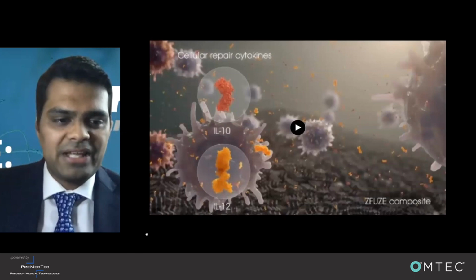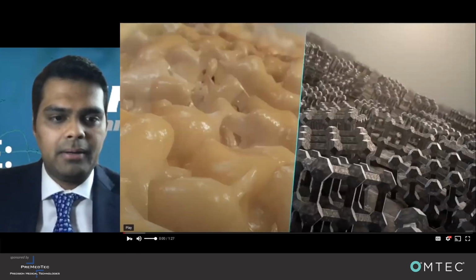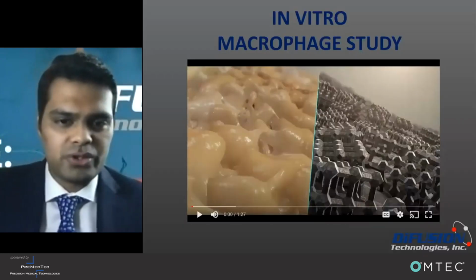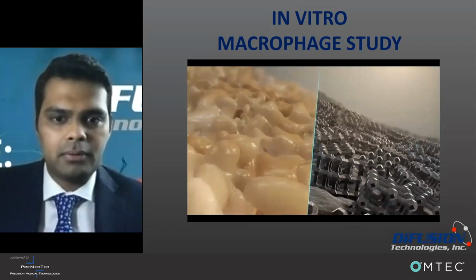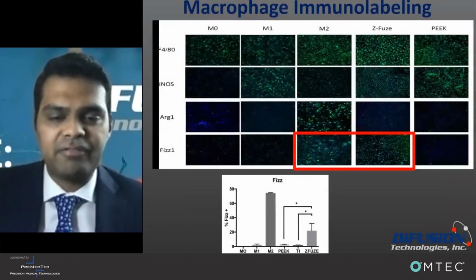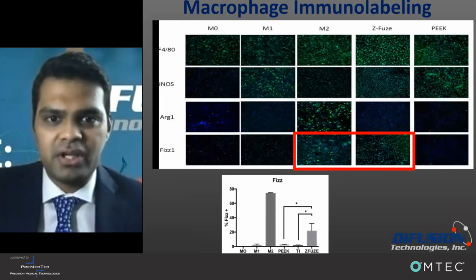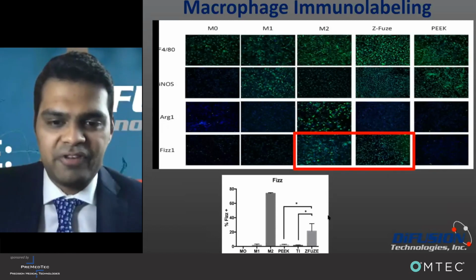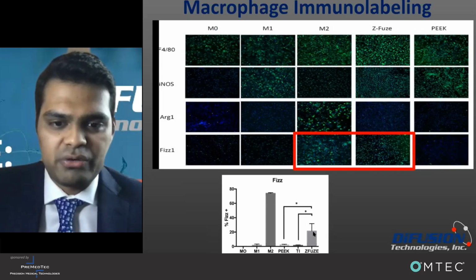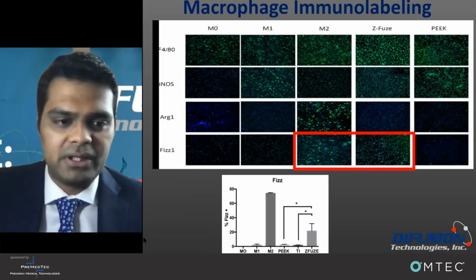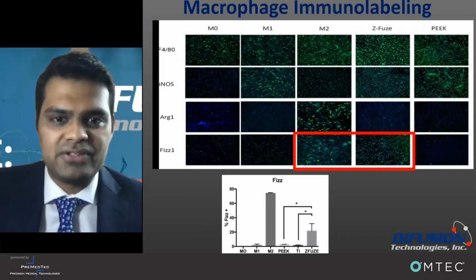So that's pretty much what happened on Z-Fuse versus PEEK, and we find that from the immunolabeling studies, we saw the same thing. We saw that there was M2 expression, which is the pro-reparative phenotype of the macrophage, on Z-Fuse versus, say, PEEK, and we looked at Fizz, which is a marker for M2 macrophages, and we found an upregulation of this M2 marker on Z-Fuse relative to titanium and PEEK, and this trend stayed pretty consistent.